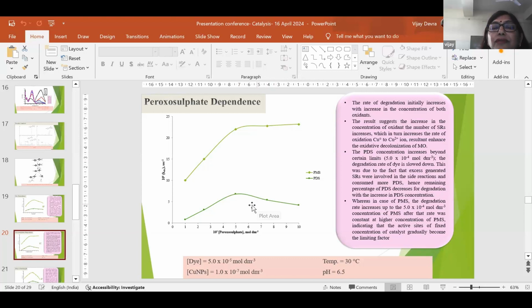But in the case of peroxodisulfate, as we increase the concentration up to 5 × 10^-4, the rate of degradation of methyl orange also increases. But beyond the higher concentration of 5 × 10^-4, the rate of methyl orange degradation decreases, which is due to the sulfate radicals being involved in side reactions. The more the peroxodisulfate is consumed, the more the percentage of peroxodisulfate decreases with increasing concentration of the peroxodisulfate at the fixed concentration of the other reactants and conditions.